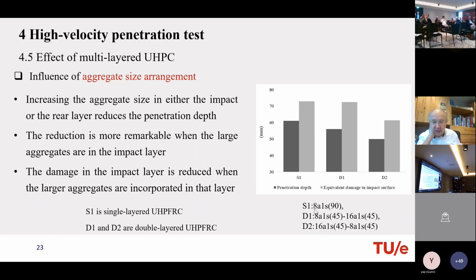Here you can see that the 8 means 8 millimeter maximum aggregate size, 1 means 1% steel fiber, and this is 90 millimeter. And here you can see with 2 layers, so 8 millimeter aggregates, 1% steel fiber, and here 16 millimeter aggregates, also 1% steel fiber.